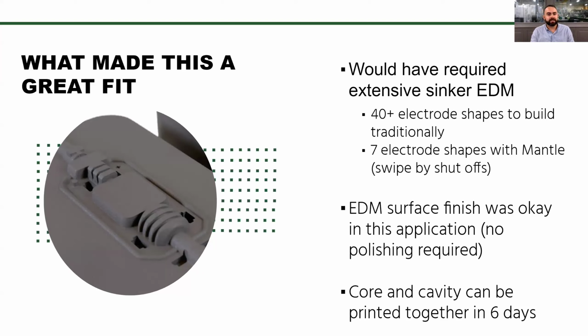And finally, the last thing was the size of the part. The benefit of allowing us to print the cavity and the core in one print allowed us to get it done within 6 days. If you have a part that's too big to print both of them at the same time, then you're basically doubling your print time from 6 to 12. So having that smaller size fitting on the print bed was another benefit as well.